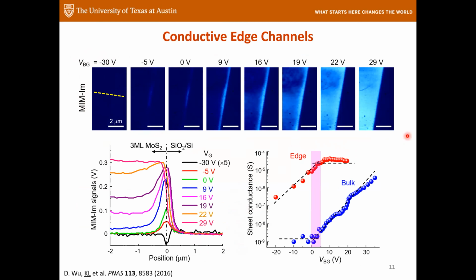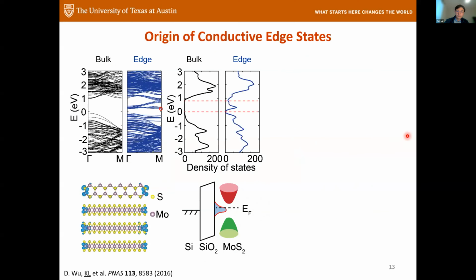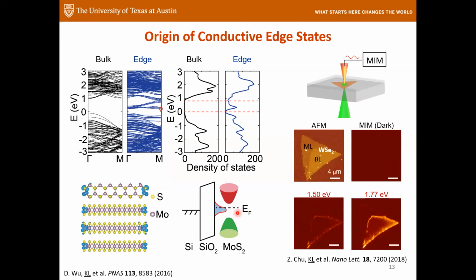I see. So you're thinking that the edge conduction channel does not exist anywhere in the gap. Correct. I have to point out that the conductive edge states you observe here are trivialized edge states, but their origin is actually topological. The origin is the so-called quantum valley Hall phase in the monolayer. In the bulk there is a valley-projected topology, but at the boundary, because of the symmetry breaking of the two valleys and many other things, it becomes trivialized.